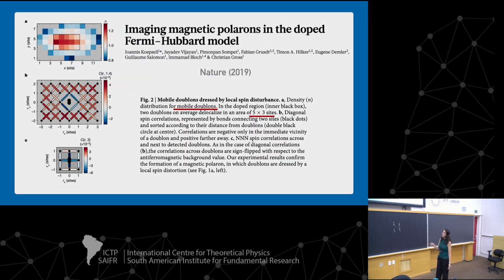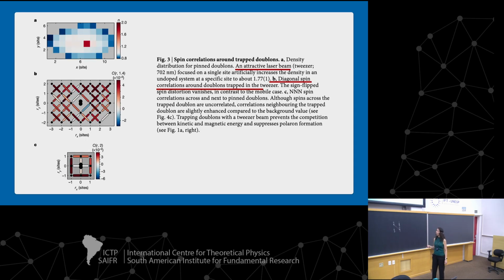And so here is this already pixelized image. It's mobile doublons. So these are two doublons that are here, and they have this in a very tight space. I've underlined it here, 5 by 3 sites. So this is 3, this is 5, and how it affects what's around. And here is the image of the correlation. So the two doublons are here in the center, and this is affecting all the environment that's around it. And it's really interesting that you have the ability to pinpoint where they are and what they are doing with the correlations around it. So once again, this is something you cannot do on materials.